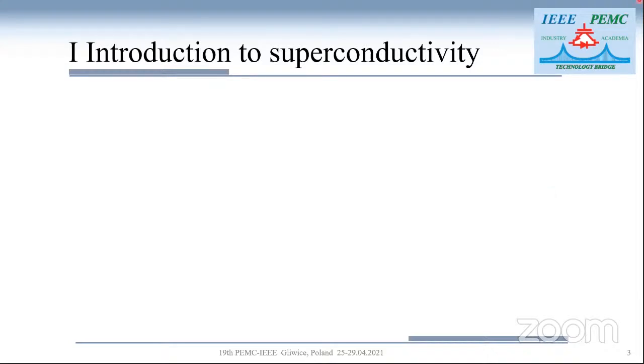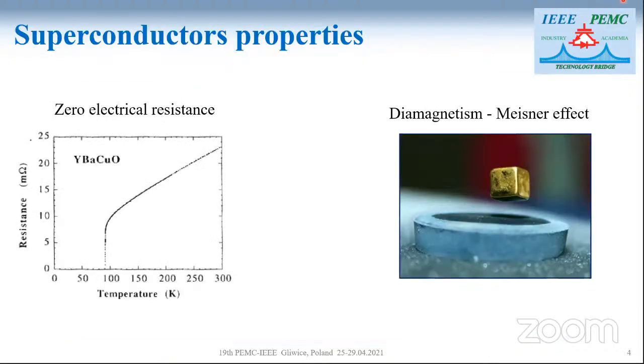I start this part with my overview of superconductivity. Two properties are really fundamental for superconductivity. The first one, discovered in 1911 in Leiden, in Holland, is a sudden drop of the resistivity below a certain temperature. This is illustrated on this picture, where the resistance of YBCO ceramic is represented. At first, the resistance decreased linearly, as for classical Ohm's law for classical materials. Then it dropped sharply, very sharply to zero. So we have the possibility to obtain circuits carrying current with no losses.